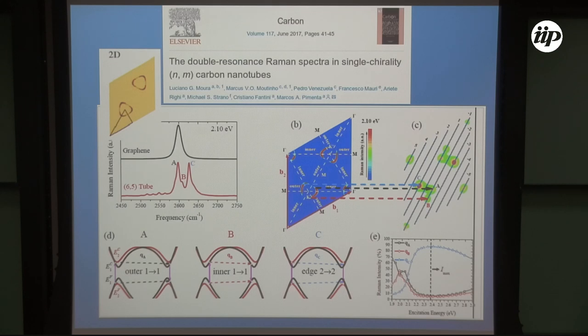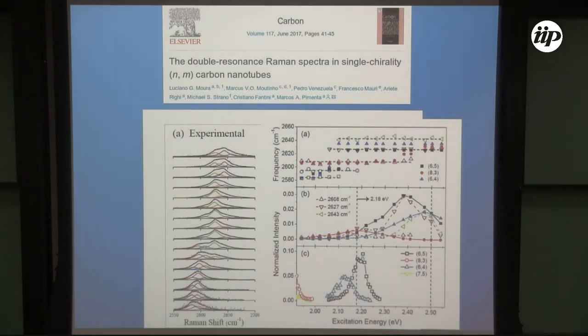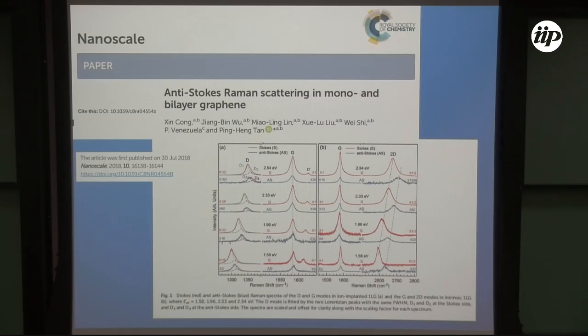Another thing that's interesting is that when you have all chiralities in a not enriched sample, what you have? You have the sum of different lines in different directions here. So you recover back the graphene's Brillouin zone, and you have back the same nice 2D band. Okay. So this kind of structure you see only if you have enriched carbon nanotube samples. I won't give much detail here.